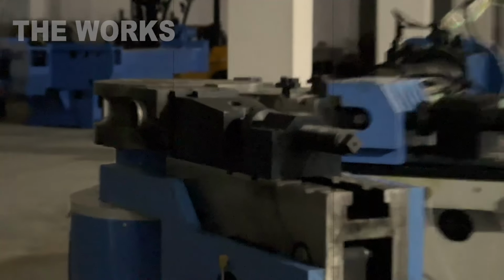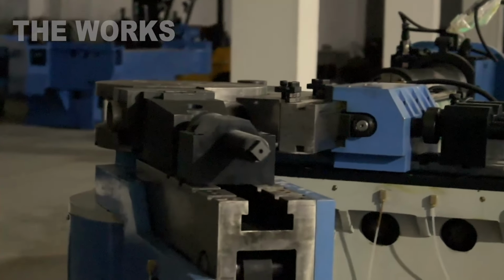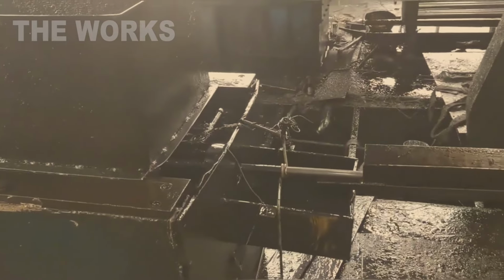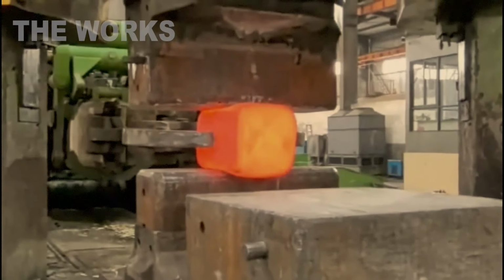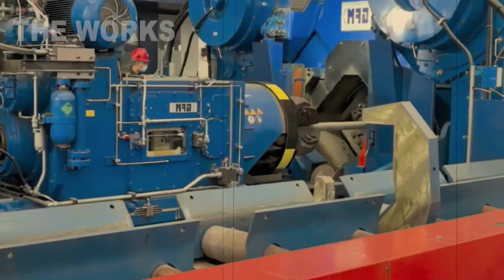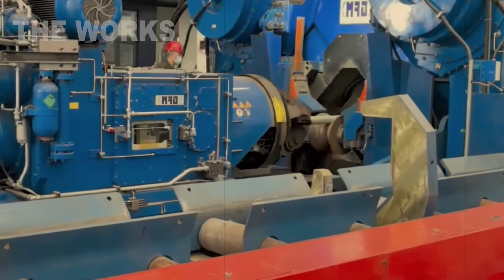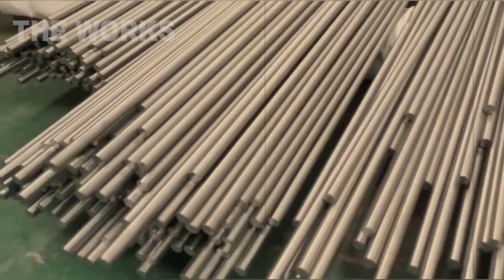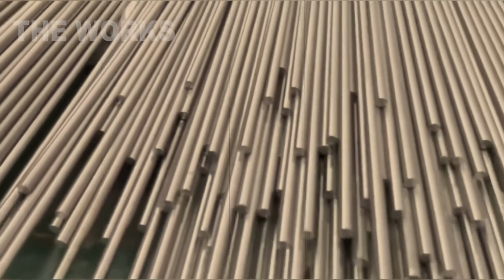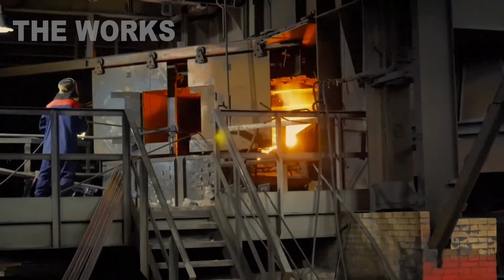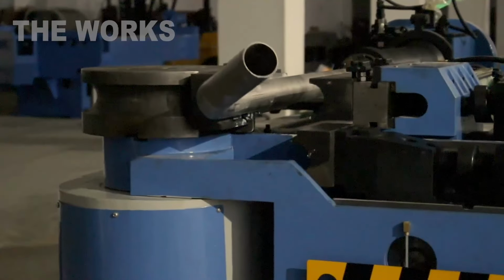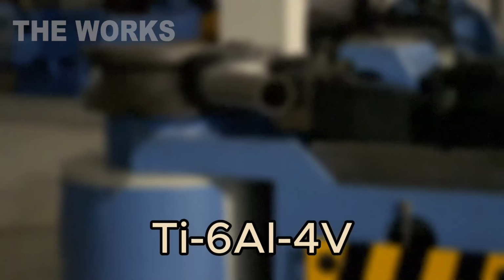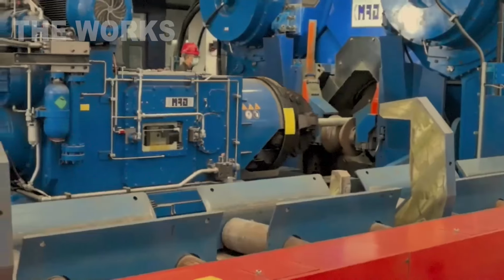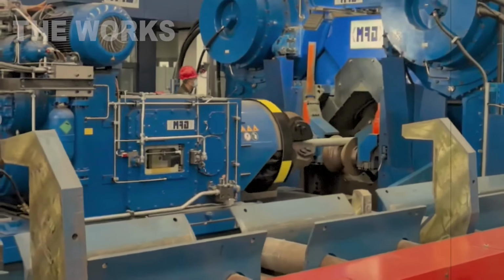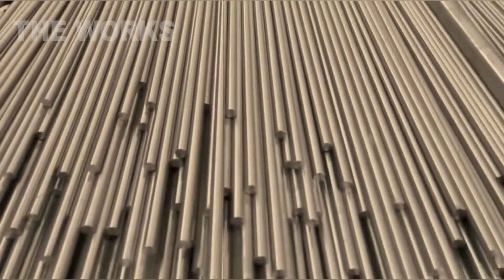But pure titanium is merely the beginning. To create materials for aviation and space, it's transformed into alloys. To molten titanium, like spices in a chef's dish, other metals are added. Aluminium for lightness, vanadium for strength, molybdenum for heat resistance. Thus is born, for example, the most famous titanium alloy, Ti-6Al-4V, which became the workhorse of the aerospace industry. These alloys are remelted several times to achieve perfect uniformity.